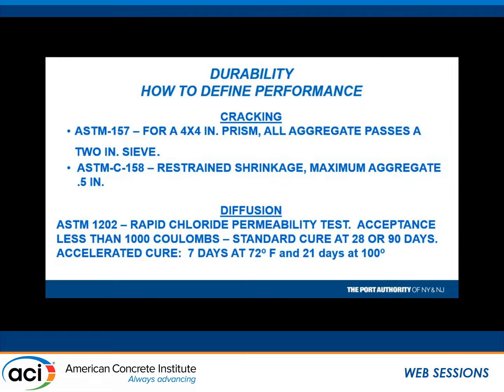Again, we decided to go to an accelerated test because nobody wants to wait 90 to 120 days to get Coulomb numbers below 1,000. Now, if you stick with the 28-day requirement for 1,000 coulombs, then you're going to have to put up with accepting silica fume or metakaolin. So we said, well, there's no way we want that. So we went with this accelerated test, and we do this on all our jobs now.